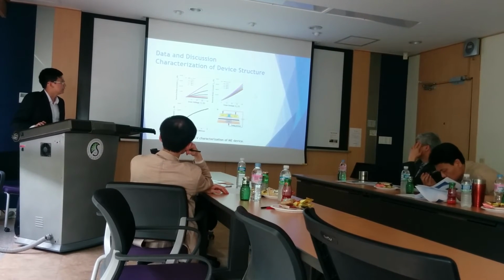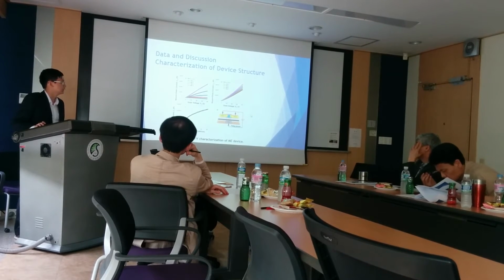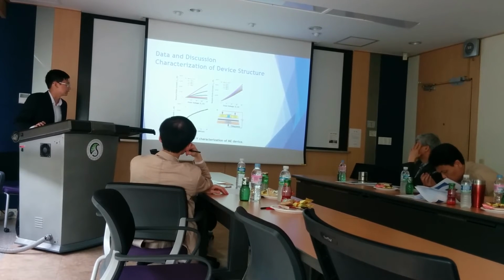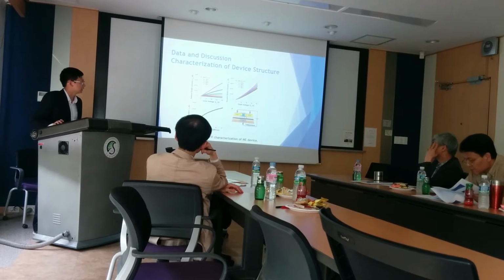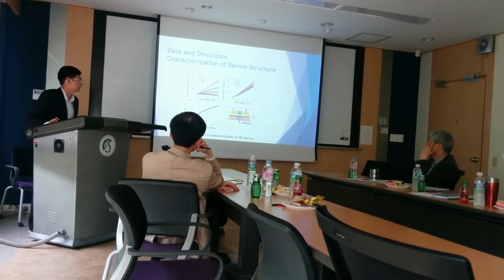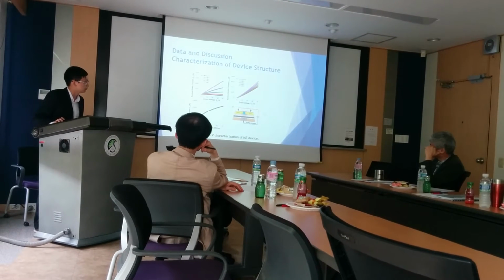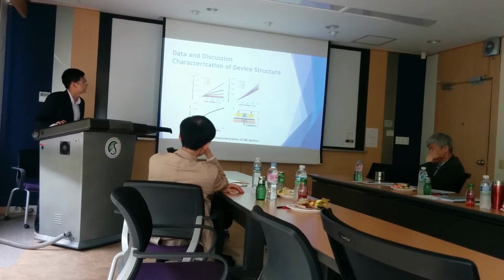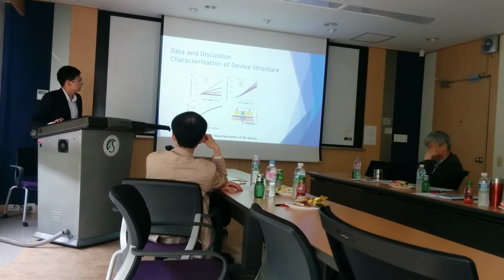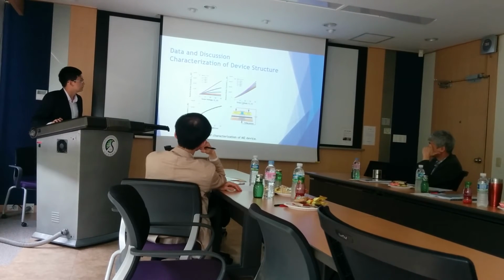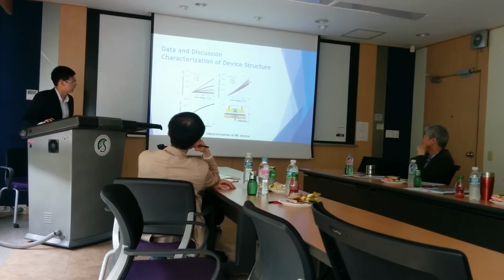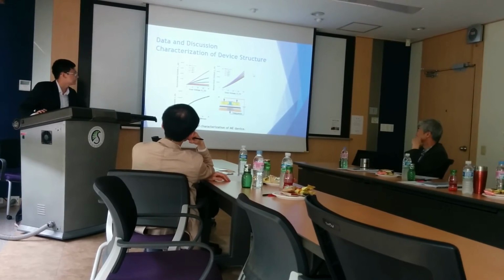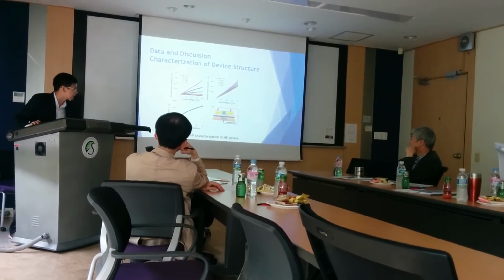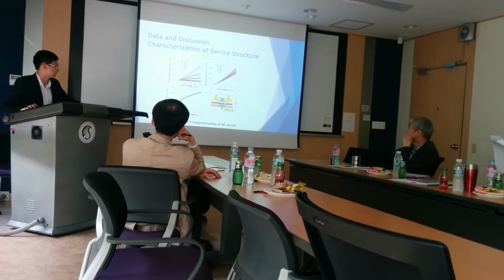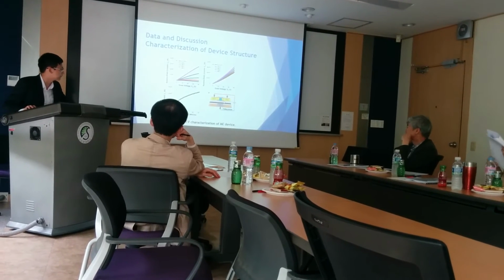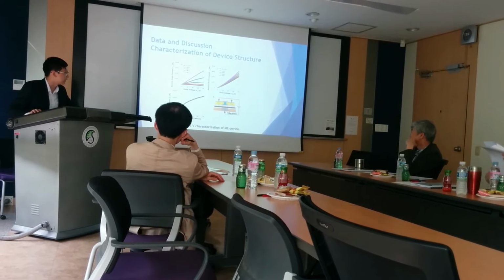To achieve the polarization in the PVDF-TrFE, we succeed by the forming process, as you can see in figure 2D. We execute it at 80 degrees for 2 hours at -40 volts to make the polarization inside the PVDF-TrFE. And as you can see in figure 2B, there is no saturation of the current at different gate biases. That means there is a large hole density at the interface of the pentacene, and as a result, there is no effect of hole accumulation from the gate bias.